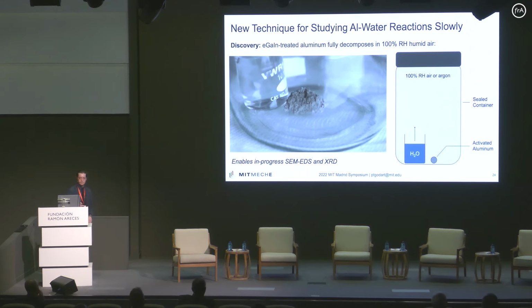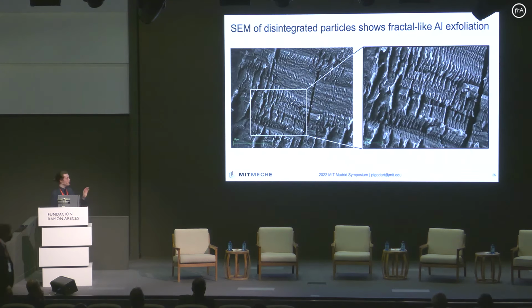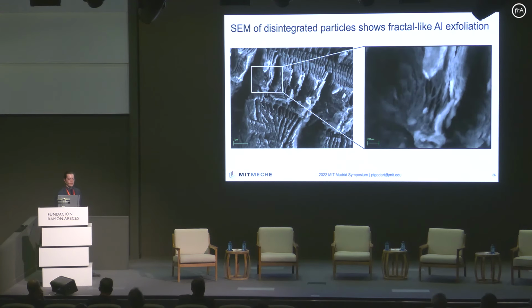And what I discovered is that, if we do this gallium and indium treatment, apply water vapor in this case, or even liquid water, and then immediately stop the reaction, we see that the aluminum is disintegrating along the microstructure. And it does so in this fractal-like exfoliation process that is self-similar all the way down to the nanoscale, as you can see on the right image over there.